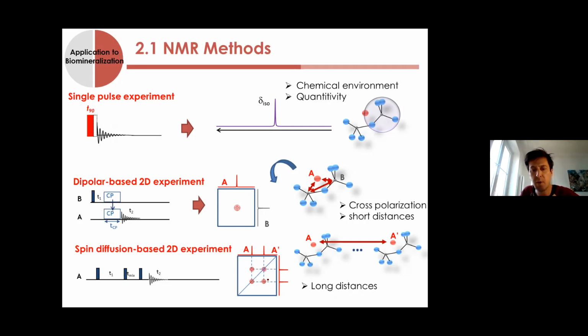And with the 2D experiments, you can see here that, for instance, species A is linked to species A prime just by the observation of some cross peaks in that case.